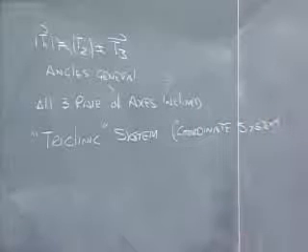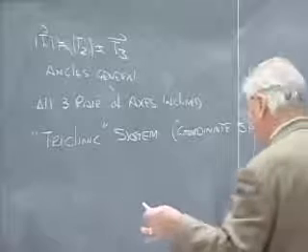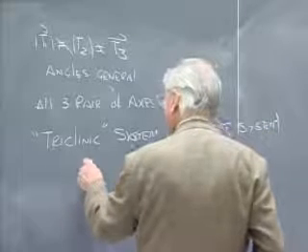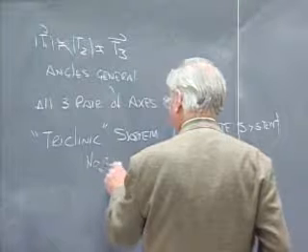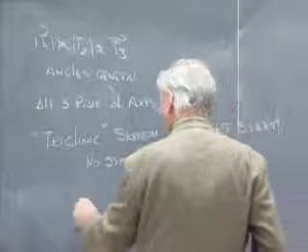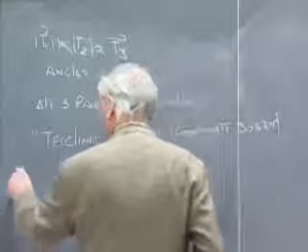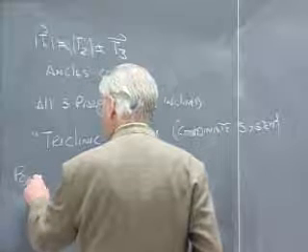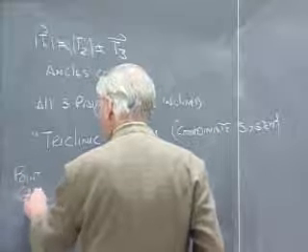So this is as general as things get, and if this is the shape of the lattice, there is no symmetry, which is the same as saying that the point group, the only point group that can fit into such a lattice is point group 1.